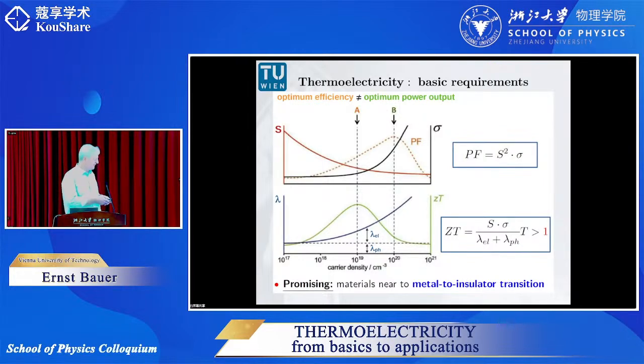So everything what I said is summarized here in this diagram, as you can see. Here on the x-axis, there is indicated the charge carrier density. And on the y-axis, we do have different quantities, like the Seebeck coefficient, which decreases like 1 over n, where n is the charge carrier density. We can see that for very small numbers of the charge carrier density, 10 to the power 17 or 10 to the power 18, we have a large Seebeck coefficient. But on the other hand, as you can see here, the electrical conductivity indicated here as sigma is quite small.